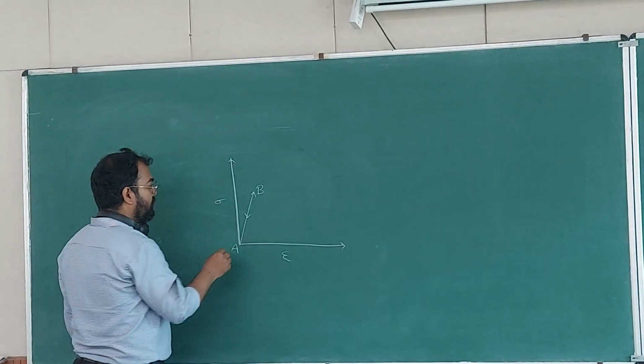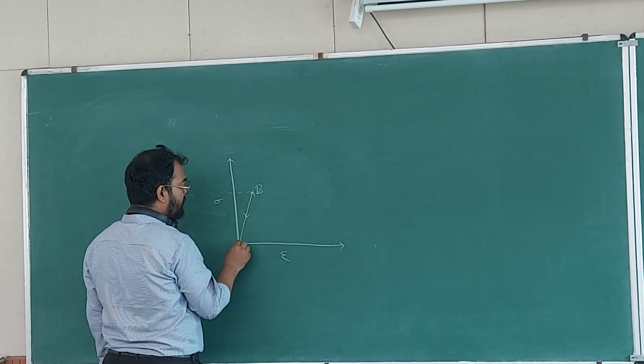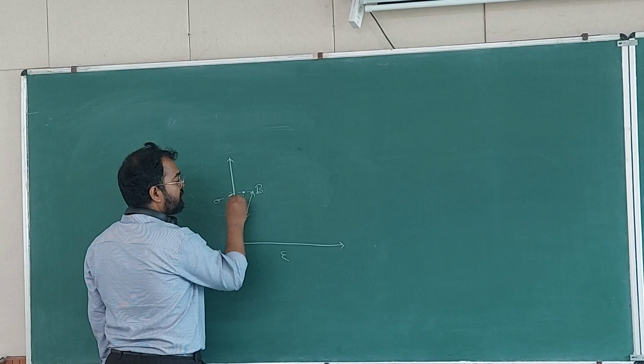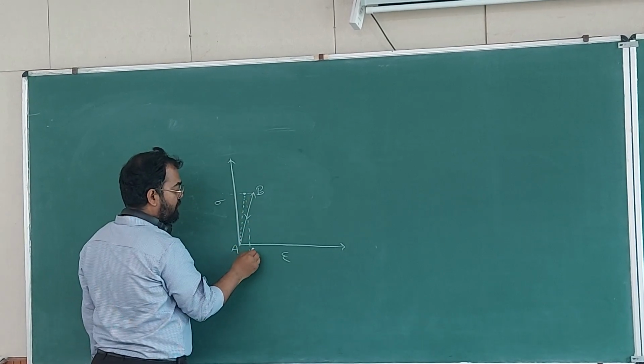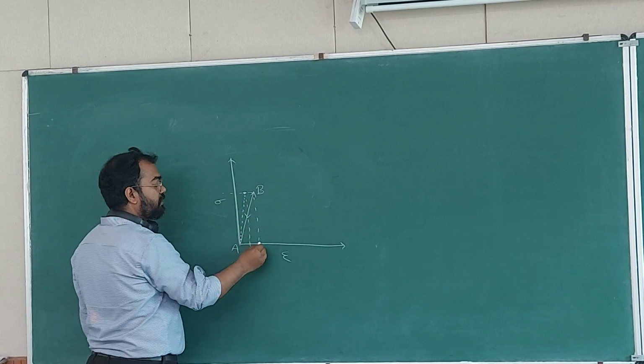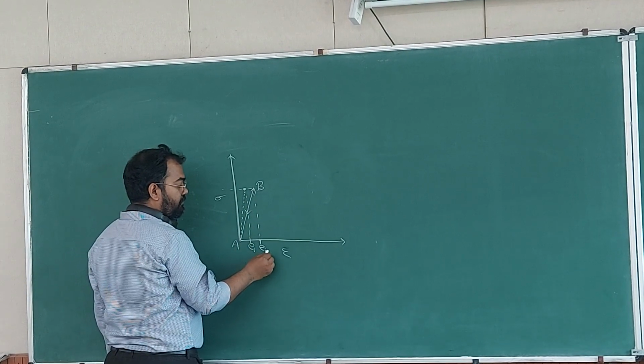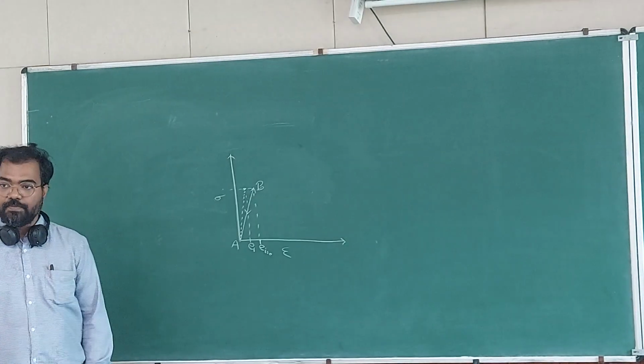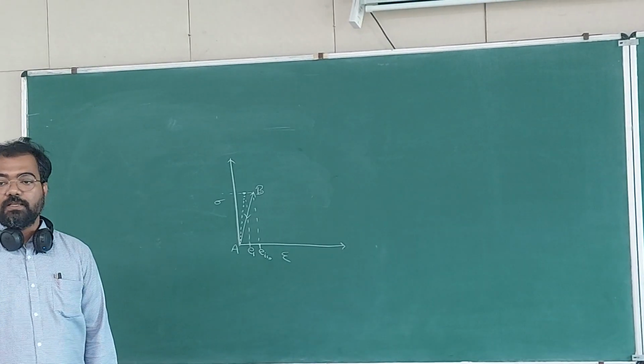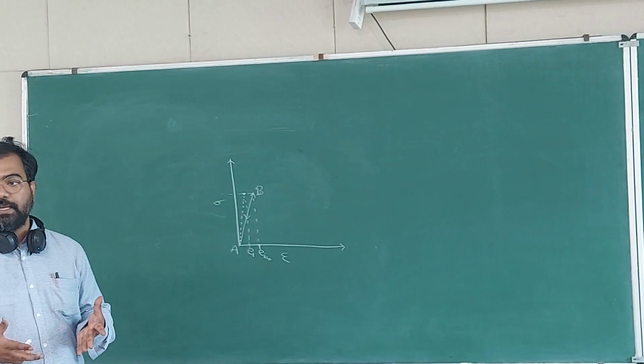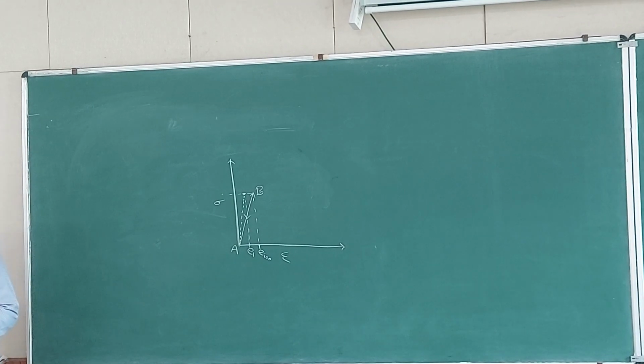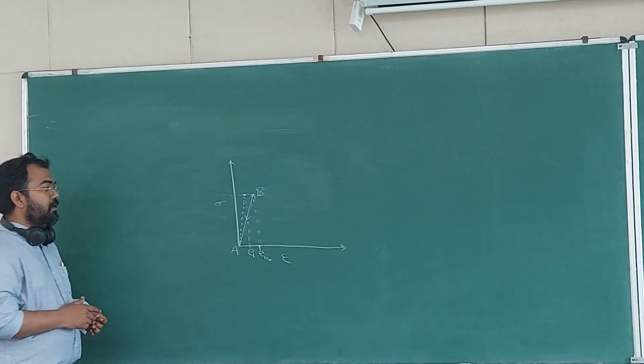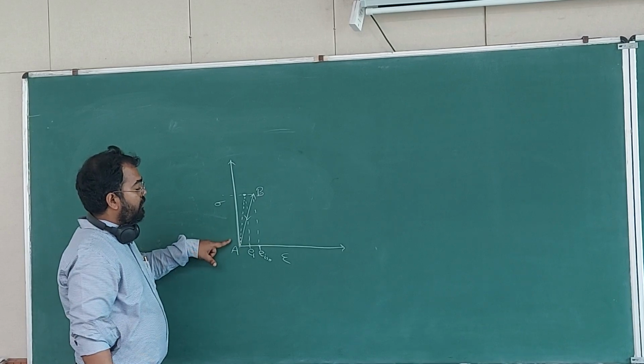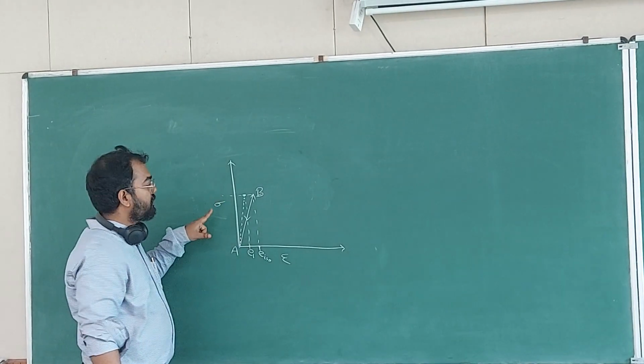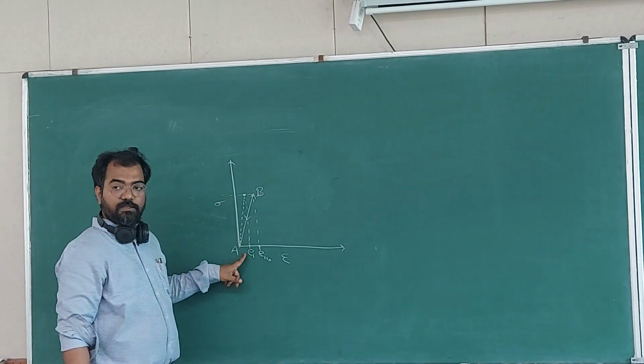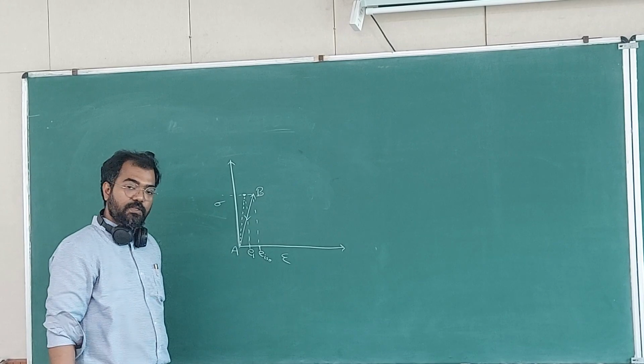But if I apply the force sigma at a very high rate, then it will not get the whole strength, but it will get something lesser than what it achieved at isothermal condition. Okay. So isothermal meaning that all the events which are happening inside the material are in equilibrium with the surrounding. Okay. So if I apply very fast the force or displacement on it, then it will not achieve the strain it would have achieved in case of isothermal loading.